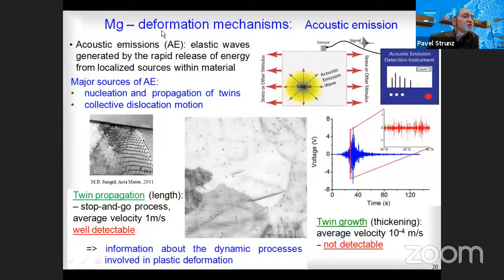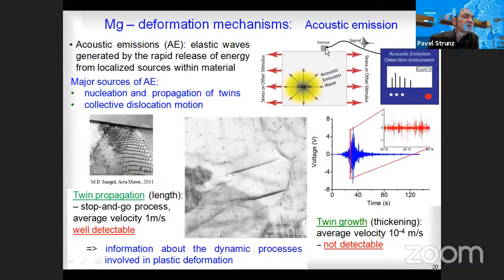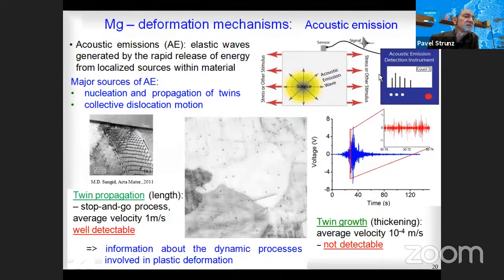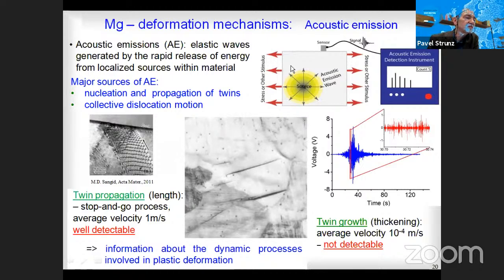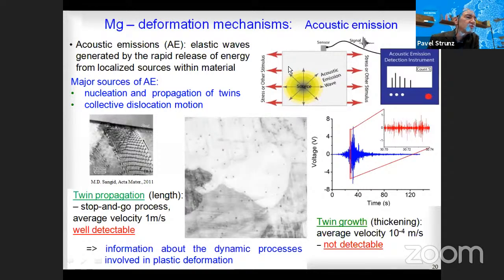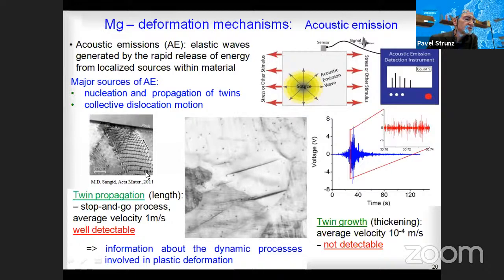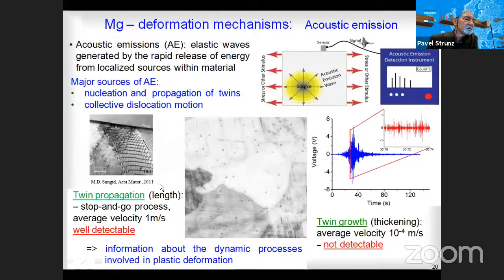It's also very advantageous to combine neutron diffraction with acoustic emission. When you put a sensor for acoustic emission on your material and you deform it, you can hear some sound. And the main source for this signal comes from nucleation and propagation of the twins or from collective motion of the dislocations. So, detecting this signal, you can gain some information about the dynamic processes which are involved in plastic deformation.